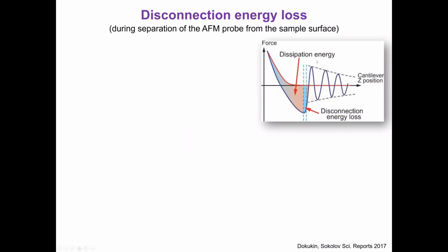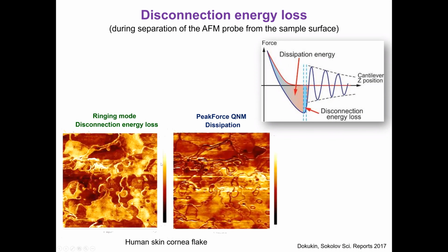So, disconnection energy loss. This is another interesting thing, because regular dissipation energy, for example in PeakForce QNM, is calculated as the integral between approach and retraction curve. And our disconnection energy loss is literally the part of this area when the probe starts disconnecting from the surface. So it's literally from the moment of loss of equilibrium till the last moment of energy loss, due to probably either a broken neck or some molecule stretched from the surface. So it is really tiny. As a result, we also expect pretty high resolution, because at this moment resolution is defined by the area of contact, and the area of contact is much, much smaller than at the full load force.